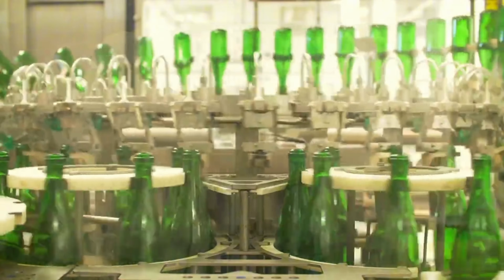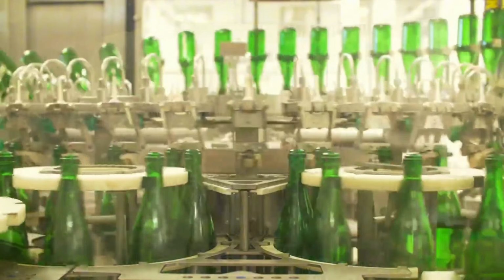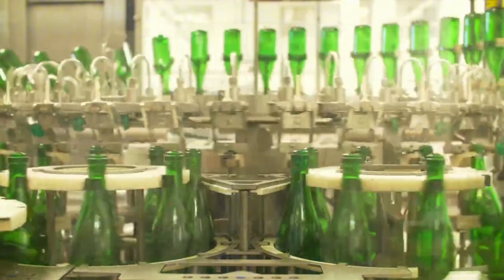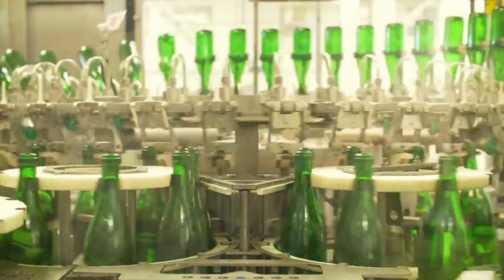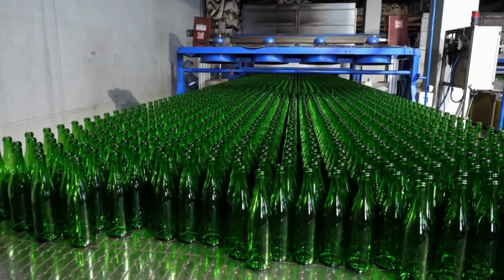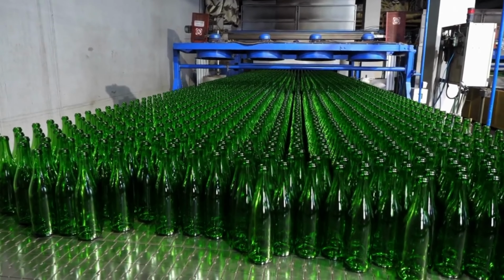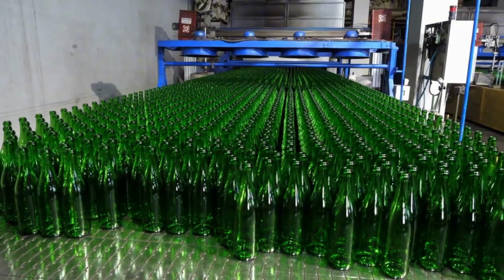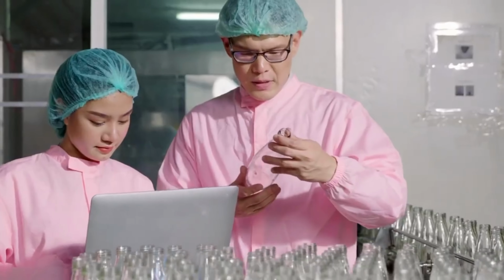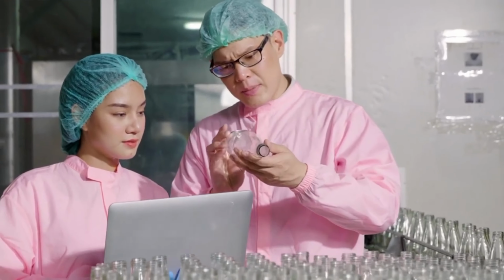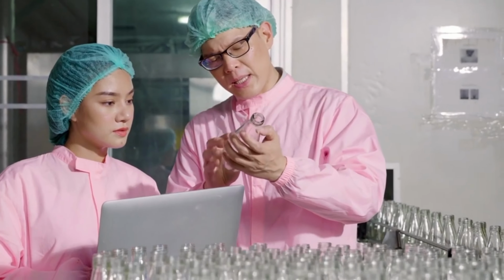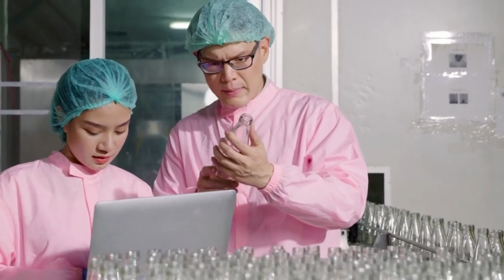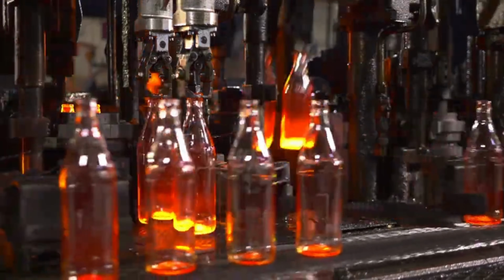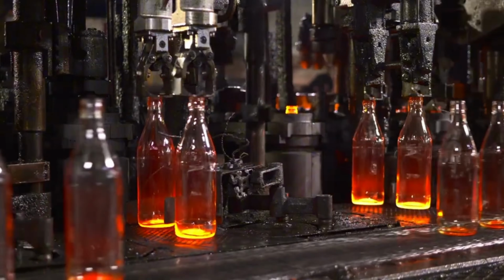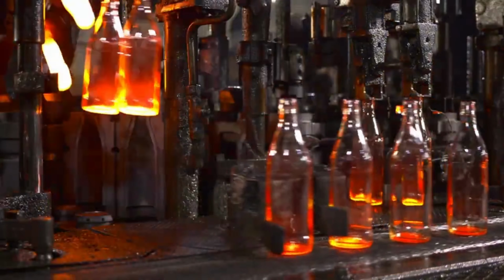They now appear clear, green, amber, or blue, depending on additives such as iron, chromium, sulfur, cobalt, or carbon used to tint the glass. And from here, the bottles undergo some of the toughest quality inspections in manufacturing, because the stakes are high. Bottles must withstand internal carbonation pressure, transport vibration, capping torque, and thermal shock from hot fills, so sophisticated inspection.